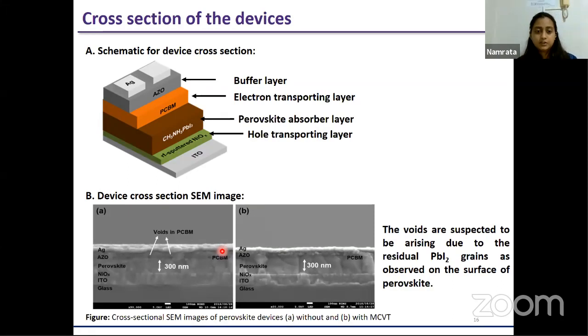So here, when we look at the device cross section, in figure B, this is the cross-section image of the perovskite which was annealed under the methyl ammonium chloride vapor treatment. We can see that we have quite uniform grains and a smooth interface without any defects. Whereas when we observe figure A, it has the perovskite that was annealed without any atmosphere. We see that the grain boundaries are not well defined, and additionally we can see that there are some defects at the interface, especially a void in the upper interface that is between the perovskite and the ETL, or the ETL in this case is the PCBM.